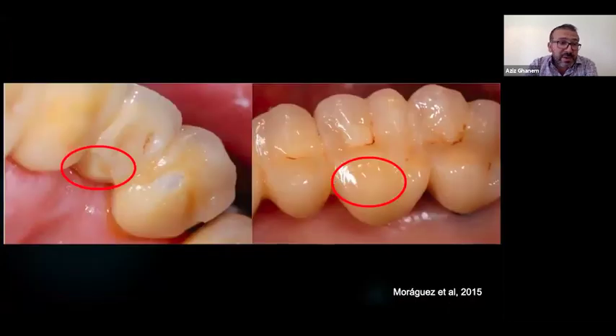Zirconia, when first introduced into the market, was mainly used for core material, and it showed a high success rate in terms of strength. But the main problem, still up to nowadays, is the chipping of the dental porcelain. Okay, the chipping. As you can see, there's a chip. Well, some of the chipping doesn't affect the function of the restoration, and some of it really affects it and needs replacement. However, in the literature, the recommendation is to replace any defective restoration.